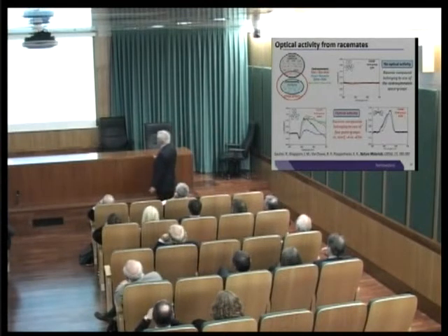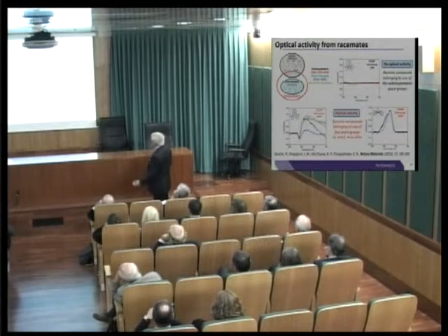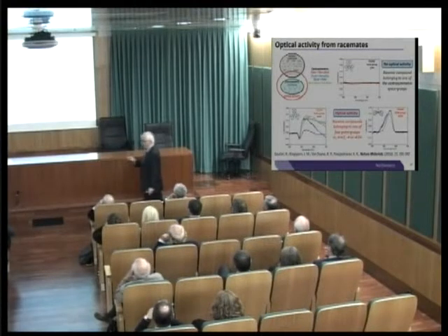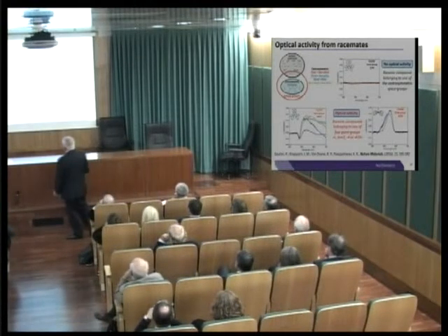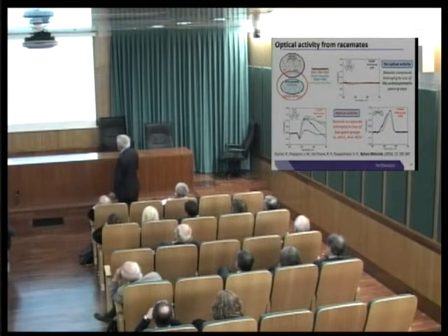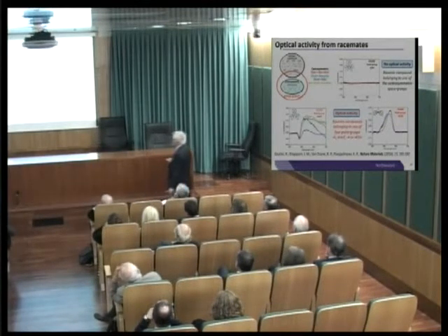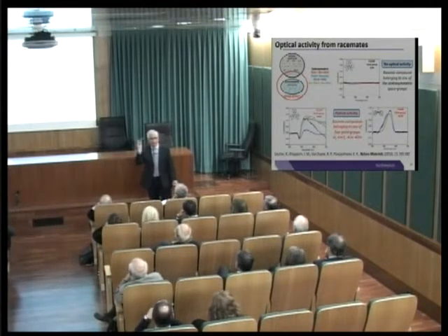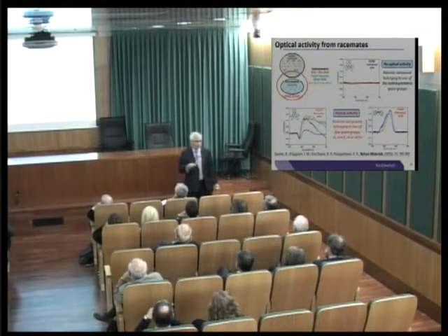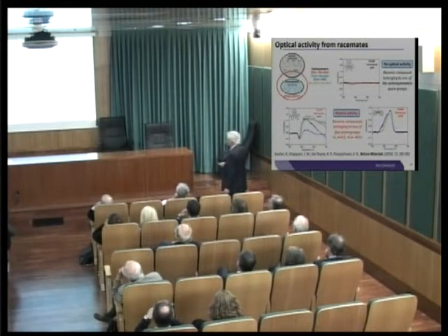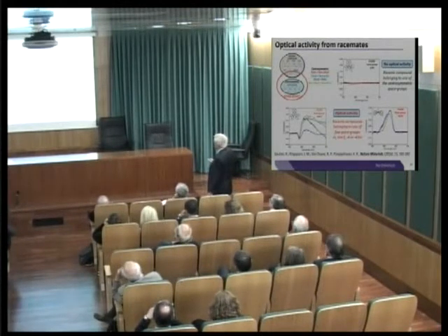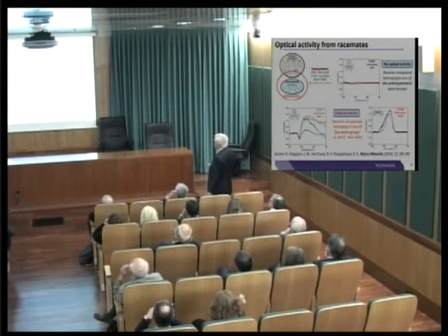it crystallized in a centrosymmetric structure, and this is the circular dichroism spectrum, essentially. This is the change in absorbance as a function of wavelength with single crystals aligned along those optical axes. And here's the same experiment where we had a non-centrosymmetric structure with the same cation. Four different experiments, so it's the same experiment on the same face of the crystal, so we're repeating the experiment multiple times. And in this case, if the racemic compound, you have no optical activity, and with these racemic compounds belonging to one of these four point groups, clearly one can observe the optical activity.